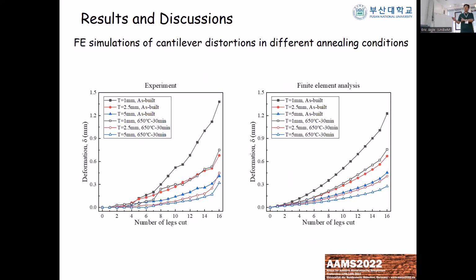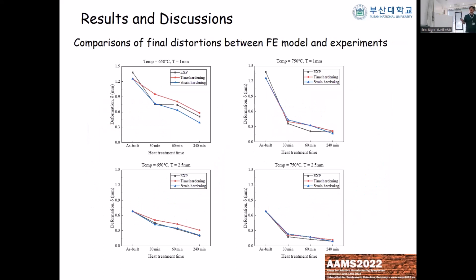Here is the experimental deformation for selected points. And here is the fitted model. We can see that here and here, those are the corresponding simulation results, and the results are very well represented. And this is the overall figure of the comparison between the experimental distortion and the one with the calibrated time hardening creep model and the strain hardening creep model. As you can see, for different annealing parameters, overall the simulation model agrees very well with the experimental data.